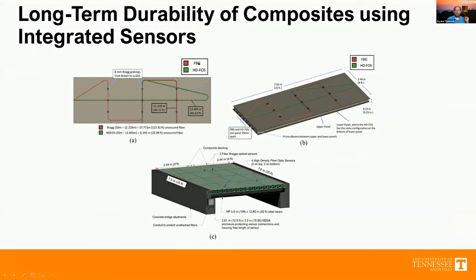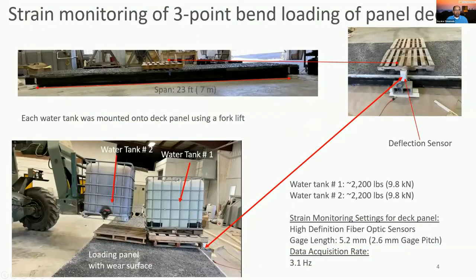This is for monitoring strains if vehicles are coming and suddenly stop. We need to understand the mobilized strains due to braking, and how well the riding surface is bonded to the structurally critical bridge deck panels. Then we have high density fiber optic sensing below for spatially resolved strain. And we also have smart joints for joining materials between the decks and the supporting beam elements. We also did a lot of proof of concept tests before we actually moved these bridge deck panels to the site.